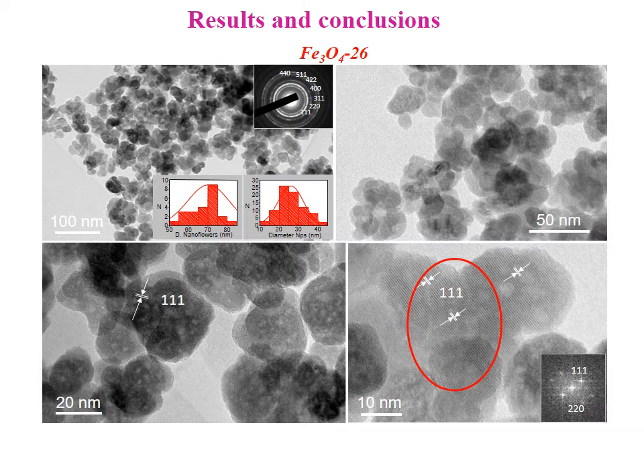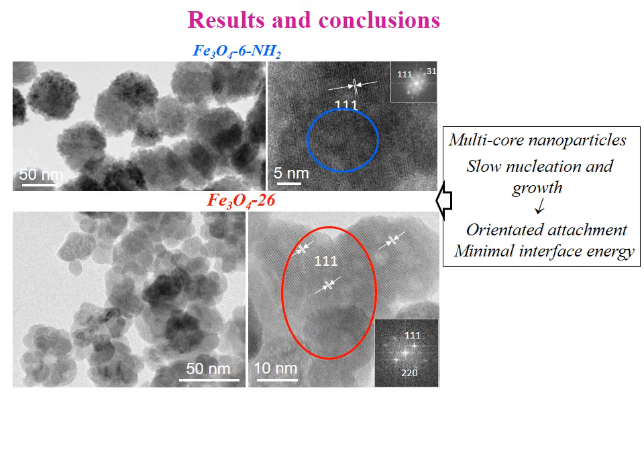According to that, the X-ray diffraction shows narrow maxima. Also, the magnetite 26 sample is representative of a multiple assembly, not of an individual core. This shows that in both cases, the oriented attachment of the particles can be related to a slow nucleation process.